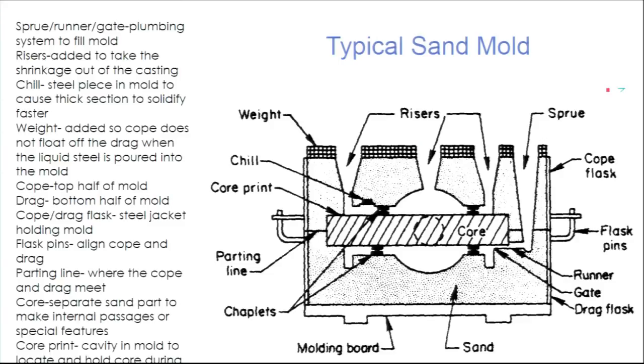if I want to make this valve body, this is really clever because I can make these holes in the casting itself. What I do is I make a mold out of sand, and I hold the sand together with an organic glue so that when I pour the steel in, the mold lives long enough for the steel to solidify, but then there's enough residual heat in the steel to burn all the organic glue away so I get the part. But to make this part, I not only have to have a hole in the sand that looks just like this part, I also have to have a plumbing system to get the liquid metal in. And then when steel goes from a liquid to a solid, it gets smaller, so I have to put reservoirs called risers on top of it so that it can feed that casting.